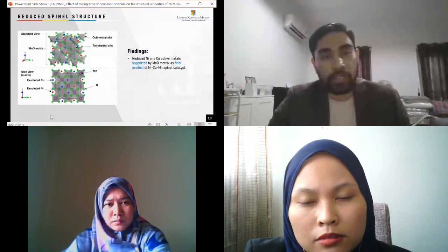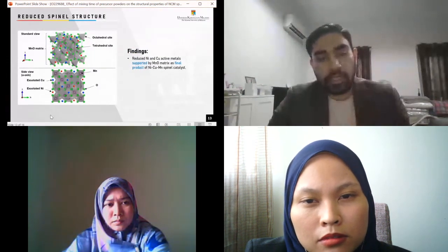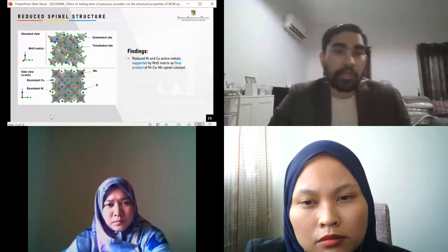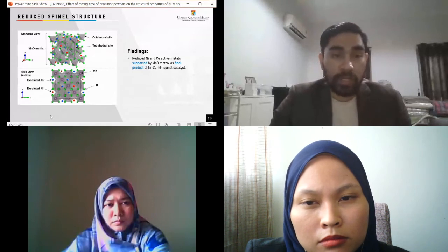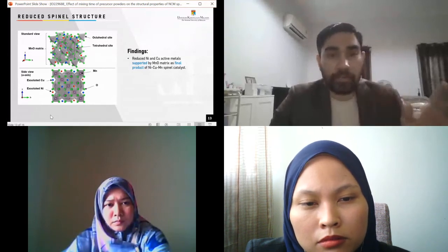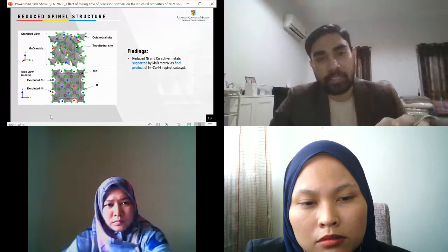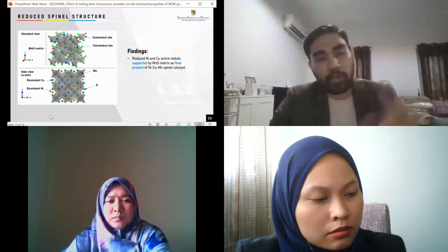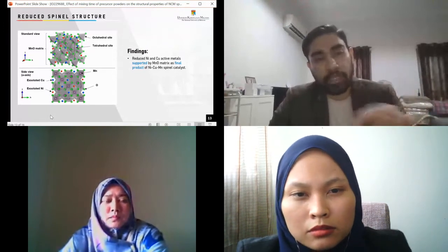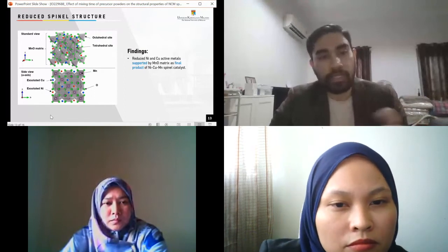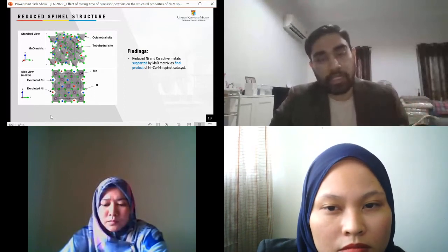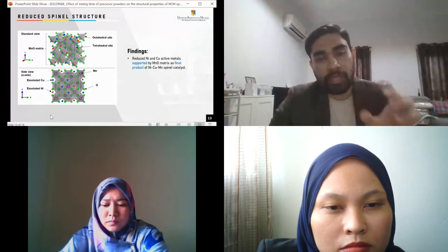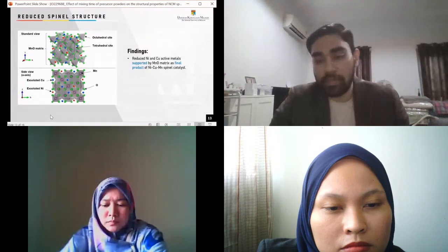Here the figure shows the final structure that is expected after the reduction process, where the reduced nickel and copper active metal, which is extracted from the spinel, is supported by the manganese oxide matrix as the final product of the nickel copper manganese spinel catalyst when it is exposed to the anode environment in the solid oxide fuel cells. So this is expected to help in combating the carbon deposition, and at the same time have high methane reforming during the solid oxide fuel cell operation.